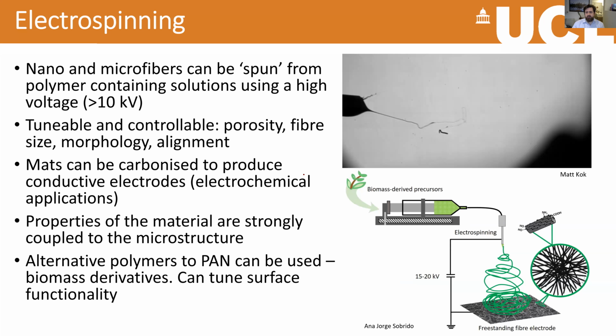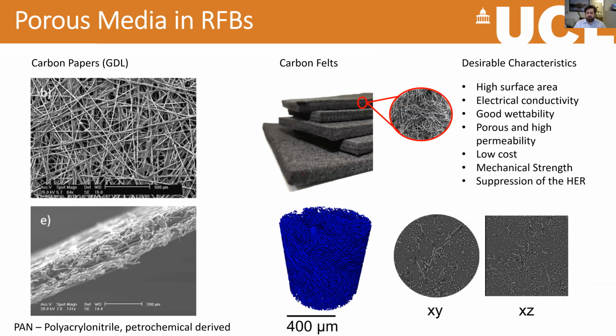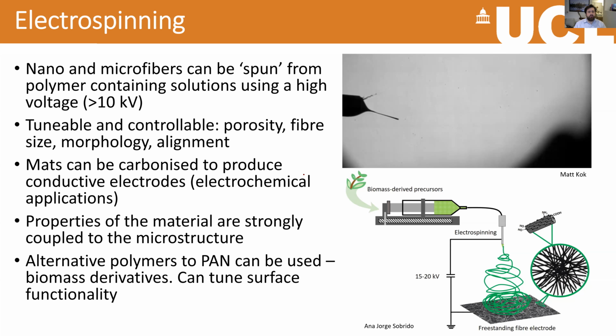One way of also making these 3D carbon structures, and something that we do a lot at UCL, is electrospinning. This is a really cool technique where you use a very high voltage to essentially spin fibers of any polymer into very small nanofibers. And so these are sort of an order of magnitude smaller than the fibers you get in these commercially woven felts, which tend to be around 10 microns in size. These tend to be about a micron or less.